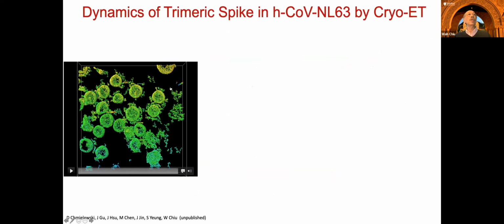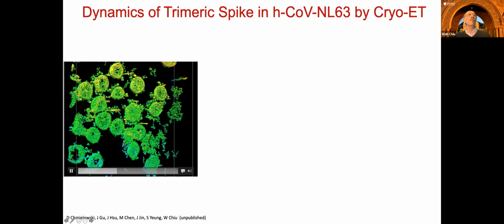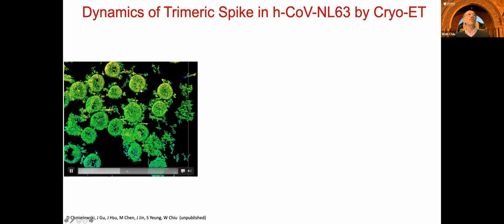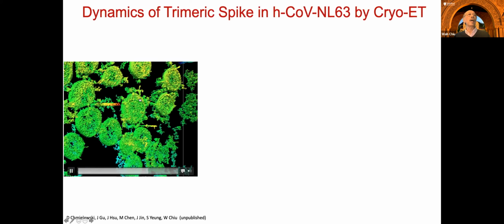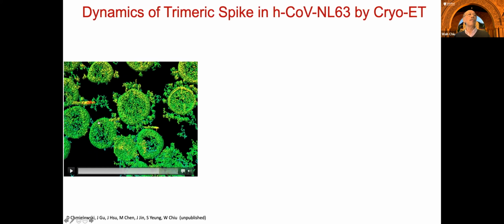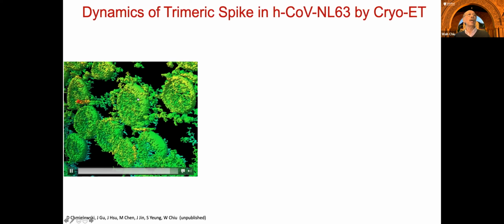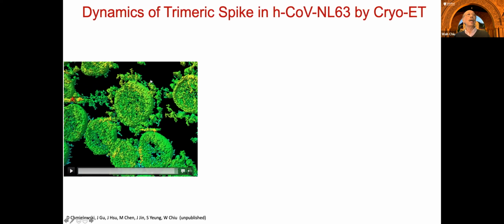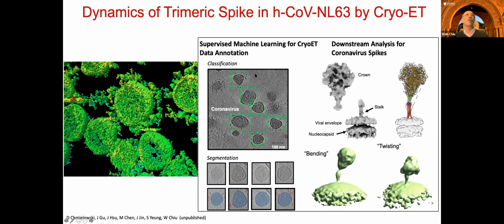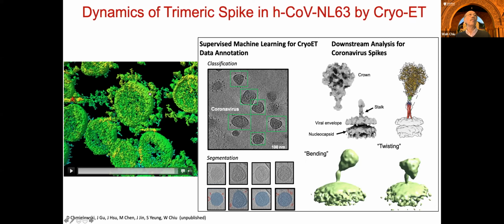The other approach is we do the tomogram. In other words, instead of taking single particle images in an area, we can do a tomogram reconstruction. This is a virtual reality display of this tomogram, and all the spikes are there. And you also note that not every particle has the same number of spikes. So they're absolutely pleomorphic. So based on this kind of work, from the 3D tomogram, we can computationally pick up the particle, in such a way that we can do the analysis of the spike.